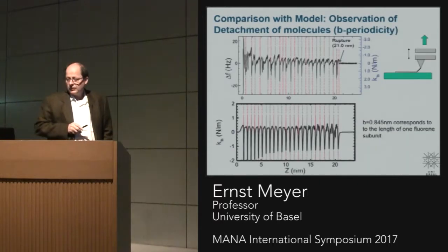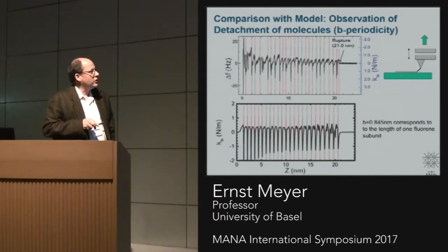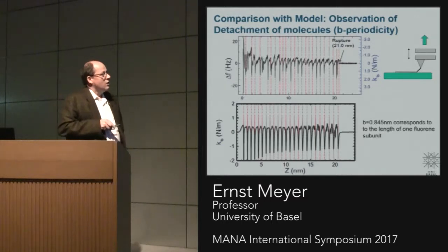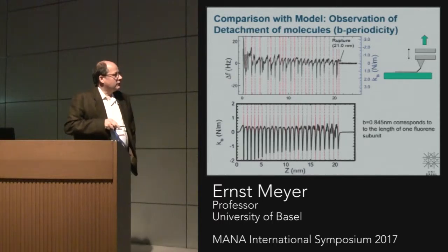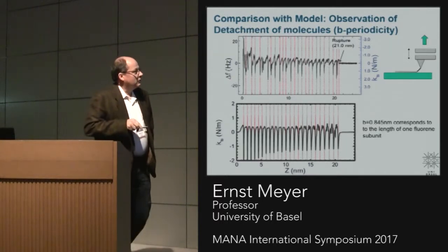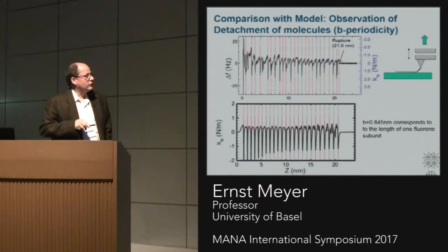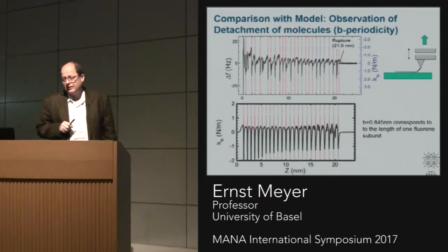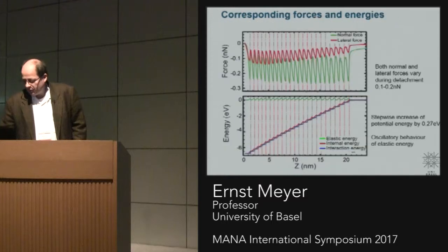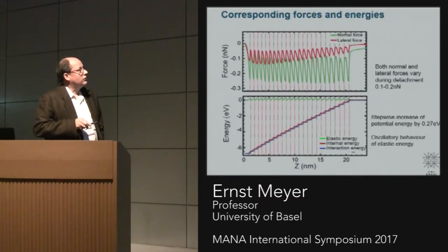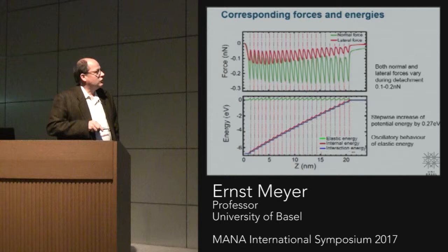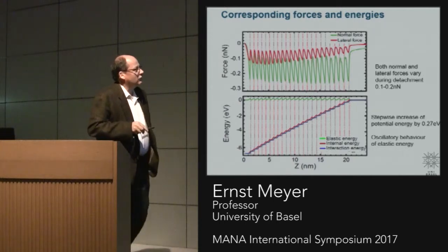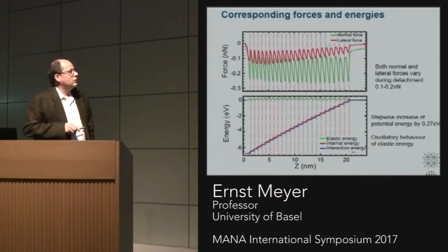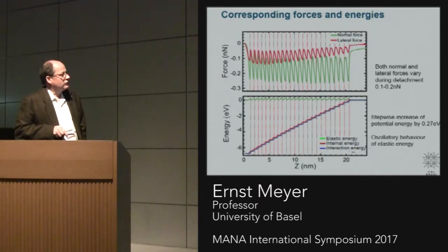Okay, so what you see here, that's the experiment again, what we discussed before. You move away with the tip and you pull basically on this chain here, or wire, and here would be the modeling, and it also shows quite good agreement. So in principle, the main effect is really this detachment of the subunits. If you plot now the forces or the energy, you can see here the force shows this oscillation because of this detachment around 0.1 to 0.2 nanonewtons.